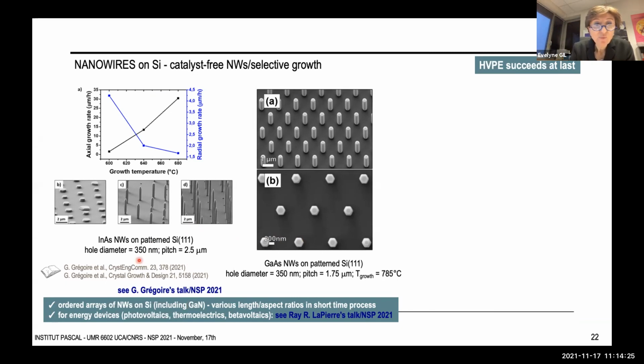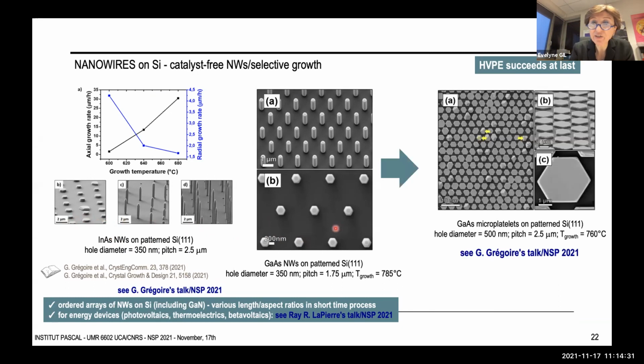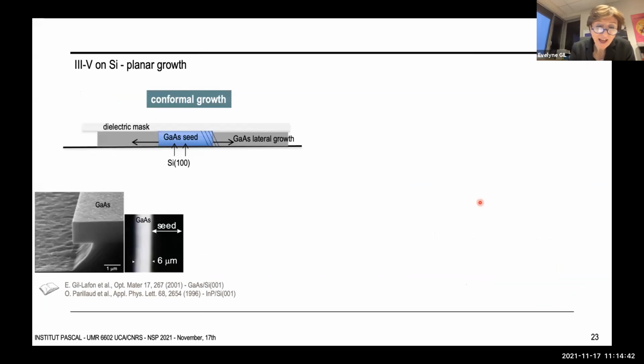You can switch to planar growth here of, let's say, platelets, as you can see here, or here for gallium arsenide, by changing the growth temperature or the composition of the vapor phase. And this brings us back to the monolithic integration of III-V compounds on silicon. And this question was quite elegantly addressed 25 years ago with conformal growth, where gallium arsenide grows laterally from gallium arsenide seeds under a dielectric capping layer.